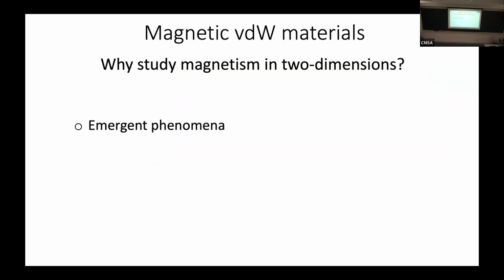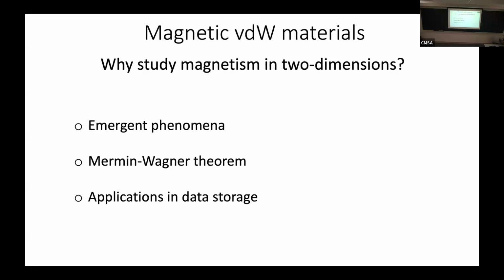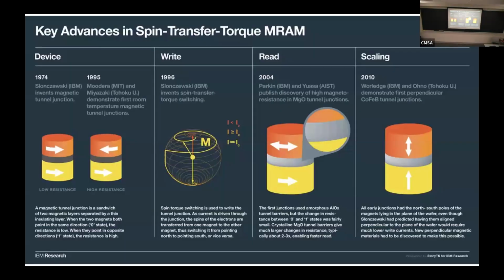There's this idea of emergent phenomena, which I alluded to before. And then there's the Mermin-Wagner theorem, which basically says you shouldn't have long-range magnetic ordering in two dimensions unless something is breaking the symmetry. And that thing is magnetocrystalline anisotropy, which just means that the magnetization vector points more readily in one direction, say in plane versus out of plane. So you can imagine some interesting physics arising where you make two or three or four layers of this van der Waals monolayer, and then you vary its magnetocrystalline anisotropy, and there could be an interplay between this thing that's breaking the symmetry and the reduced dimensionality, maybe giving rise to some interesting new physics, maybe something to explore. And there are some applications in data storage, which I'll talk more about in this next slide,